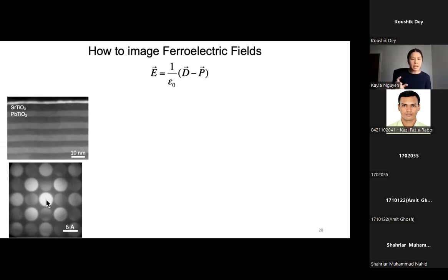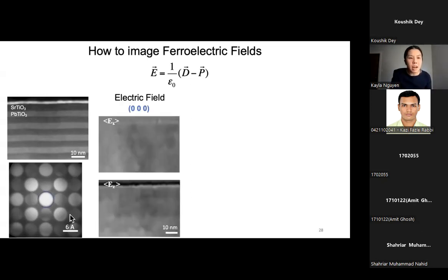When you think about polarization in terms of diffraction, in order to get polarization information, you need to break symmetry. And so you need to look at pairs of the diffraction disks in order to get back information related to polarization. However, if you only want to look at the electric field, then you can look at the center disk, because there is no polarization information in the center disk, as there are no conjugate pairs with the center disk. It's just a 0-0 disk and that's it. If we look at the change in center of mass, where we mask all of these other disks and only look at the center disk, we get information back related to the electric field.